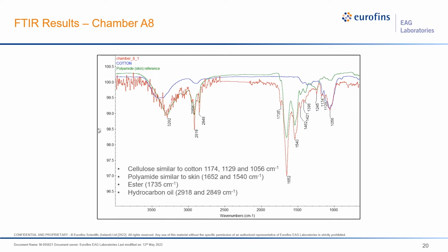Here, what we detect is a little different. First of all, we see polyamide, that's the green, and that's probably a skin flake. We see cellulose, that's in the blue here. We also see an ester, 1735, and we see some hydrocarbon oil. Now, I do want to say that although it seems like there's a lot of stuff, these are actually what we typically see with handling.